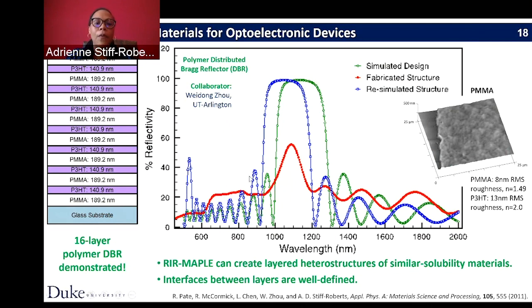We grew this by MAPLE and went to measure the properties, and we got the red curve. When we look at the red curve, the matching of the peaks with the green curve is not that good. So we went back to the simulation and took into account the surface roughness of these polymer films that are inherent to films deposited by MAPLE. And when you account for this, 8 nanometer, 13 nanometer surface roughness in the design, we got the blue curve. And there you see much better matching between the peaks in the simulation and what we measured.